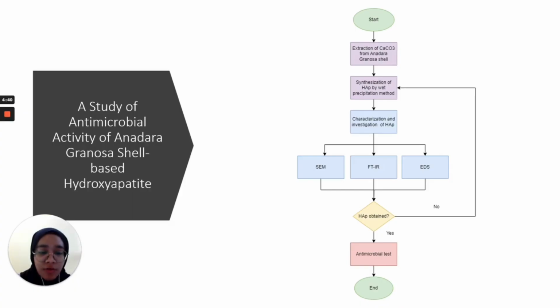This is the flowchart of my study. Firstly, we extract the calcium carbonate from the Anadara granosa shell by crushing and grinding the shell to obtain calcium carbonate powder before drying the powder inside an oven for 3 hours. And then the HAP is synthesized by the wet precipitation method. The calcium carbonate obtained from Anadara granosa is used as the calcium source and phosphoric acid is used as the phosphate source. The pH of the solution is maintained at 11 throughout this process by adding sodium hydroxide solution dropwise.